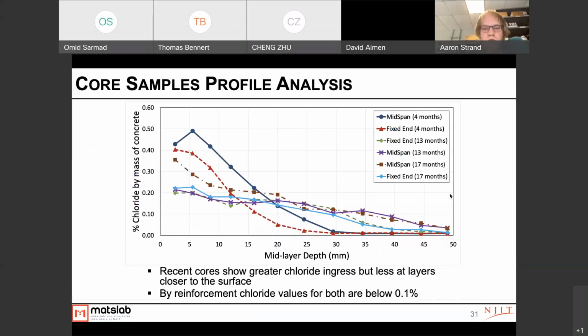So for the core samples profiling, basically we saw that within a couple months of starting the testing, we did see a fairly high amount of chloride. It was interesting to notice that as the testing continued, we did see lower amounts of chloride, but this is likely due to the fact that the cores were all taken from similar but different areas of the deck, and the natural variations in the deck may have caused the amount of chlorides to change. Also, for most specimens near the midspan, we did see typically a slightly higher amount of chloride than in the fixed ends. This is likely due to the moving load on the bridge deck causing a greater increase in the chlorides.